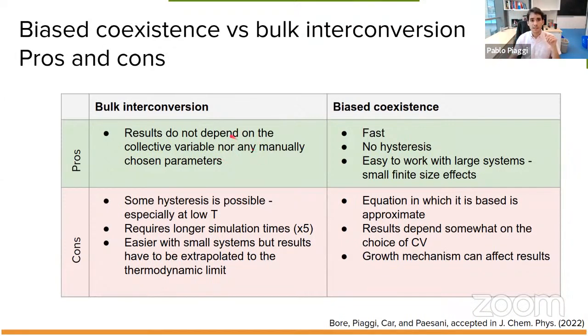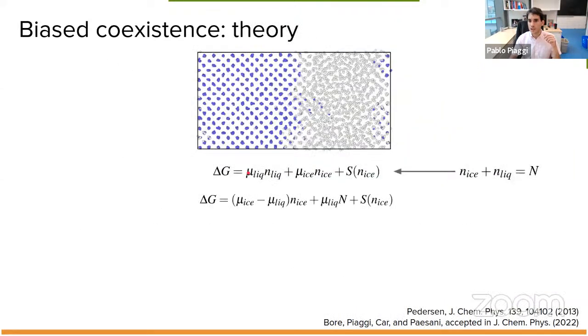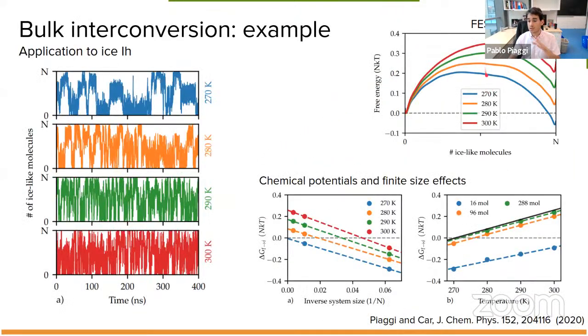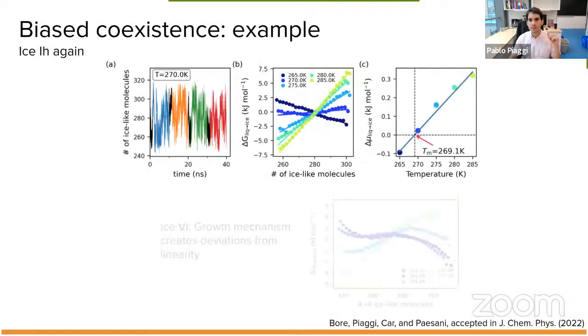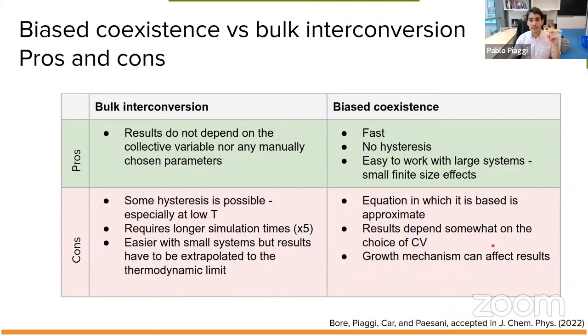And in the case of bulk interconversion, there aren't any manually chosen parameters, because one has to choose a threshold. Is this some threshold here to say what's liquid and what's solid? But the free energy barriers are so large that whatever you choose, even if you make a terrible choice, the results do not depend on that. Instead, in the biased coexistence technique, the results depend somewhat on the choice of CV. As we saw for ICE-6, the growth mechanism can also interfere in the calculation, which is a consideration.